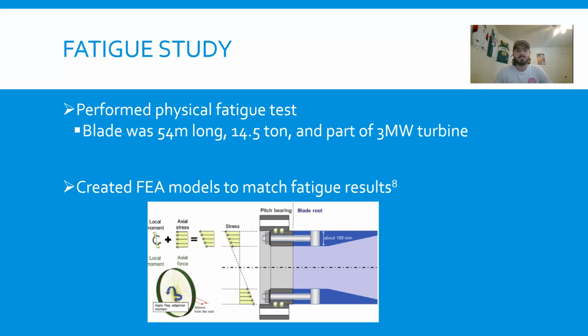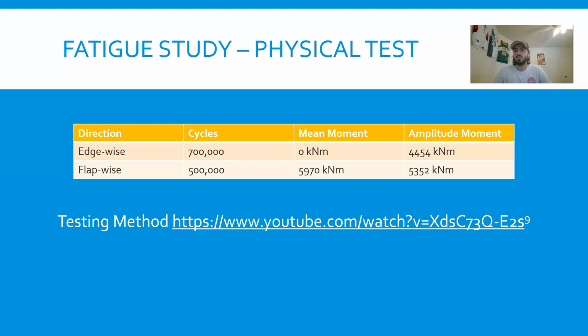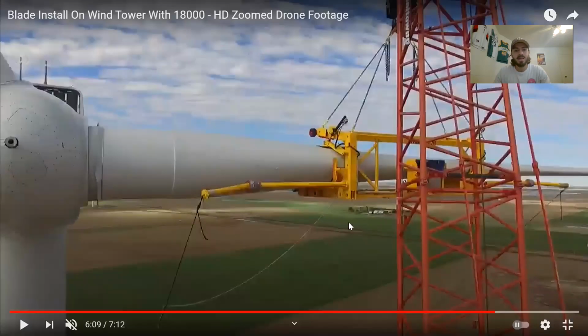as this test occurs. The type of test that is used is called dual axis resonance testing, and that involves moving the blade both in the flapwise and edgewise directions at the same time. In the edgewise direction, we did 700,000 cycles with a mean moment of 0, but an amplitude moment of 4.5 meganewton meters. And then flapwise, 500K cycles, mean moment of about 6 meganewton meters and amplitude moment of 5.3 meganewton meters. Here I have a quick little video to show you what the testing would look like, just that way you can see what it means to really be moving both flapwise and edgewise at the same time during testing.